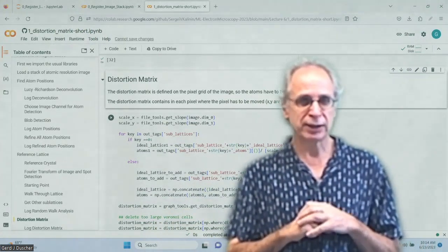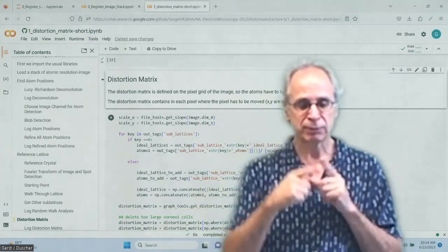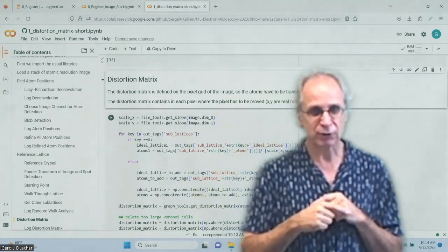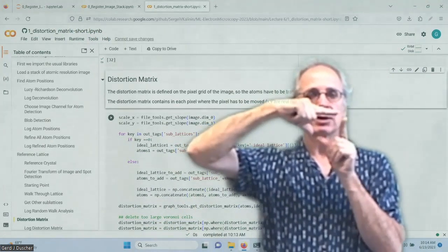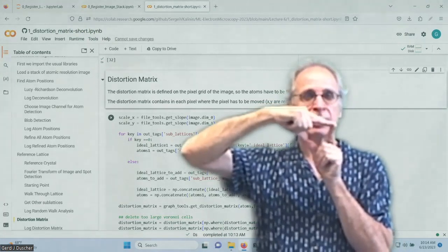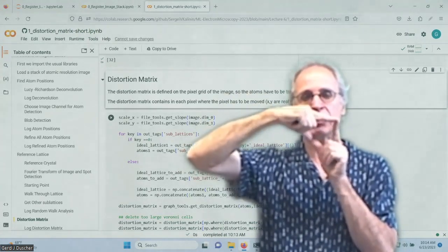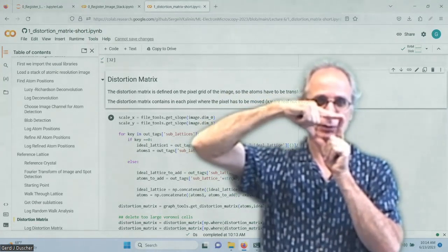What I'm doing is I'm using a Voronoi tiling of all the atoms. So I have an area that is unambiguously associated with one atomic position. And I have the neighboring ones as well, so I know how it is distorted. So what I'm doing is I undistort that Voronoi cell and then place it where it needs to be.